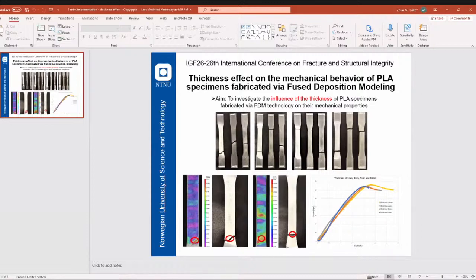Well, according to the literature review I have done, if the layer height is larger, for example, right now my case is 0.1 millimeter, if I change the layer height to 0.2, that will decrease the bonding for each layer, and the stiffness, the Young's modulus, will decrease as well by increasing the layer height. How would it affect the thickness effect as well? Oh, for the thickness effect.